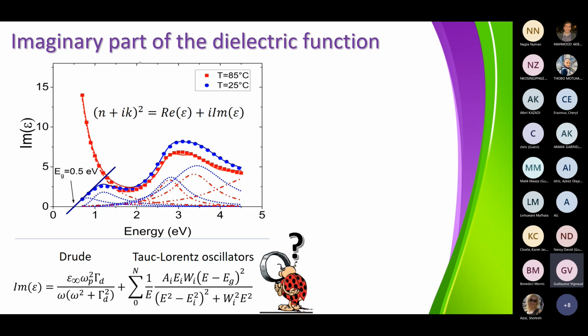Okay. But now if you look at what you get in the dielectric function, imaginary part, you can see that there is not only a tail, but there are many humps. Okay. And those many humps, you can ask yourself how they are related to your VO2. So then you need to describe those humps. And those humps, they are described by what we call the Tauc-Lorentz oscillators. And those Tauc-Lorentz oscillators, you see that they can be described by this function. It's a bit complex, but you need to understand what you have inside this type of function.